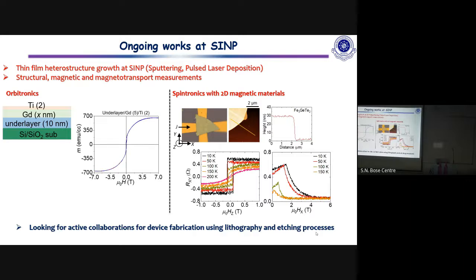Now the problem is, if we see the theory of magnetic domains, people have shown that in materials with high magnetic anisotropy, in this case the anisotropy constant at low temperature, 10 Kelvin, is roughly 10^6 joules per meter cubed, you can have these pinch-off domains embedded within the uniaxial state. But some people say that these are not pinch-off domains, but something else. So that is a very difficult situation right now with these 2D magnets.